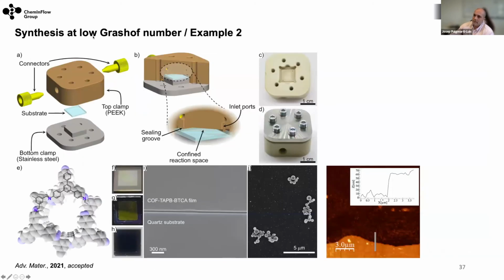We also redesigned our microfluidic device and did it in a way that we can change the surface very rapidly with different ones. So this is what you see there. This is quartz, glass, and then we can also have graphite. And we did, in this case, the synthesis of the same MOF I showed in the previous slide. What we wanted to prove is that when we do the synthesis of this MOF in the same conditions as in our microfluidic device, but in bulk, what we obtain is microcrystalline particles. But in our microfluidic device, with this low Grashof number, what we can achieve is this perfect film.